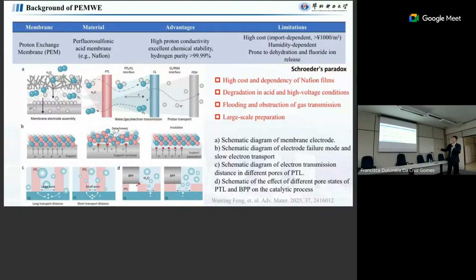For the system, it's difficult to do the transport because water and oxygen are in opposite directions. And also, for the PTL, we have a border on it. The border we use for the conduction of the electrons, and the space we use for the transport of the water and the oxygen. So the system is quite complicated. And if we have this metal here, then after a few running cycles we will have some passive layers, which cause detachment from the layers. For example, if we have full passive layers, then the catalyst will be completely gone. So we need to take methods to control the corrosion rate. Otherwise, the system fails.